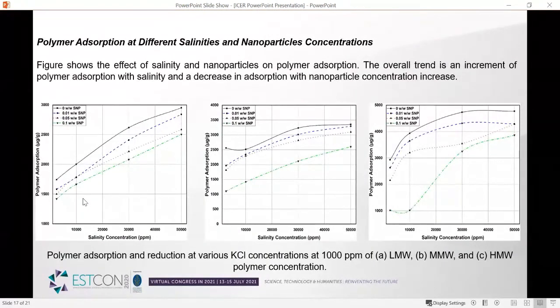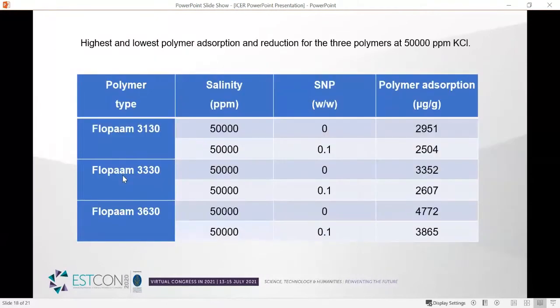Also, on the other hand, this figure shows the effect of salinity and the nanoparticle on the polymer adsorption. The overall trend is an increment of polymer adsorption with salinity and decrease in adsorption with the nanoparticle concentration increase. And actually, this is a summary of the lowest and highest adsorption condition in this work for each polymer.